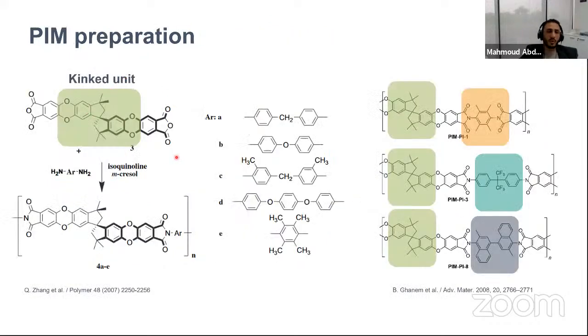Now, I just want to show you what PIM preparation looks like and how we can prepare a porous polymer. Simply, to have a porous polymer, you have to have something called a kinked structure. I'm not sure how familiar you are with organic chemistry, but a benzene ring is considered a flat ring. If you have a flat ring, when you make a polymer out of this, you get a very linear polymer. Imagine you have more than one chain of a linear polymer, then the packing on top of these chains will be very tight. So you won't have any porosity between the chains.